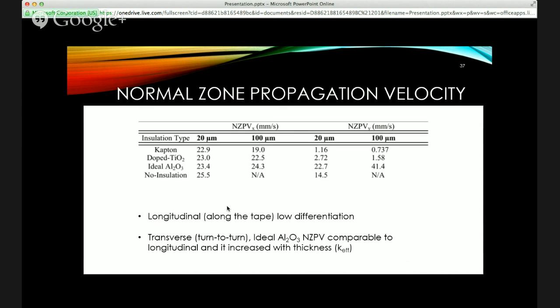And then for the non-insulated cases, it has a high NZPV in Y as well, and this is because of its thermal conductivity. However, even though its thermal conductivity is much higher than the ideal case, one of the issues that it runs into is because there's no insulation between the different layers, it has current sharing issues. So whereas it may current share earlier than the ideal case would.